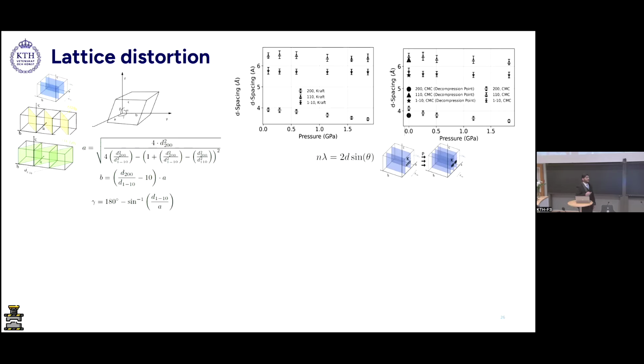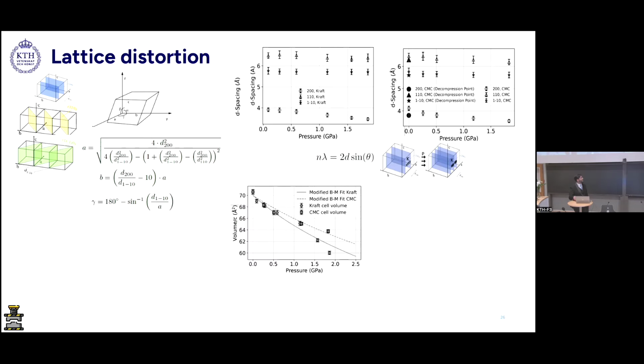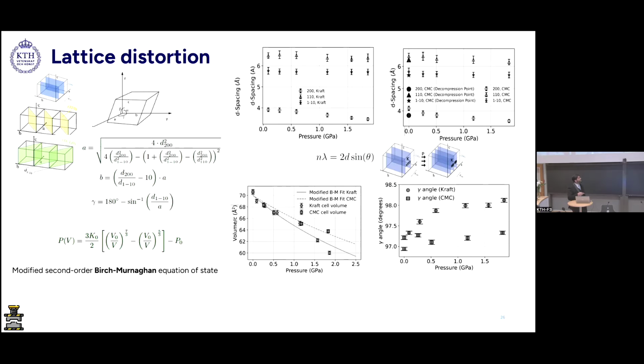So we calculated the cell parameters for the possible volume contraction. After some geometrical rearrangement, we could plot the volume data for the cellulose cell in both kraft pulp as well as carboxymethylated pulp. We tried to fit a mathematical curve through it, which turned out to be the Birch-Murnaghan equation of state, just to have a mathematical edge on this project. Also, the gamma angle, as you can see from the cell volume, seemed to be increasing in the beginning, and then it was asymptotic. When it is increasing, that means the majority of forces acting on the lattice planes are shear forces. Later on, at more than 1 gigapascal of pressure, it was more asymptotic, which means that the only force acting on the lattice was compression force.